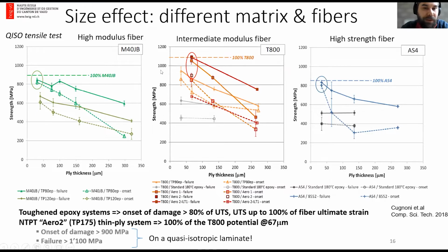which means a very, very high onset of damage. The onset of damage is very important because below the onset of damage, the composite is safe to be used in cyclic loading. And this onset of damage defines also the fatigue limit of the laminate. So this means that by having such a high onset of damage, this structure made of this material could sustain very high stress cycles at a stress level of 1 gigapascal, which is very, very interesting.